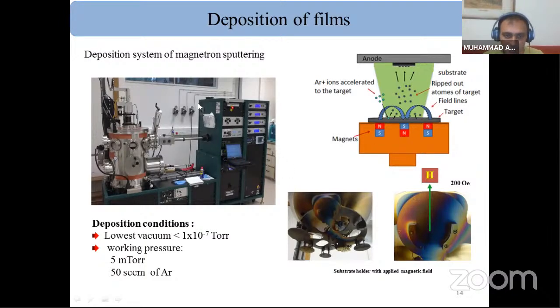While this is a pictorial description of our sputtering system. Here is the main vacuum chamber with a high vacuum. It has a capacity of 6 targets. These targets are connected by either DC field sources or RF field sources. This is a load lock. We can replace the sample from the main chamber without breaking the vacuum of the system.